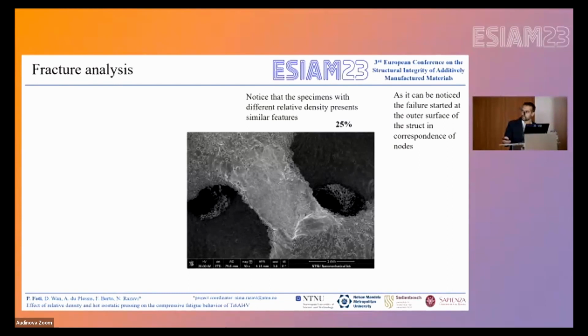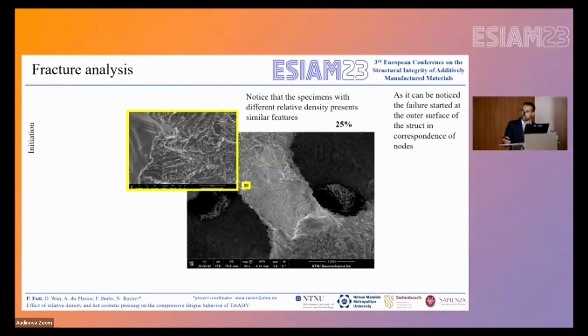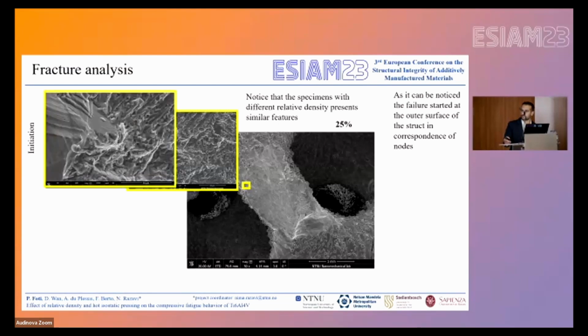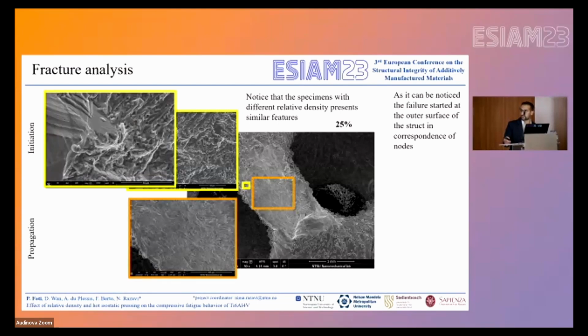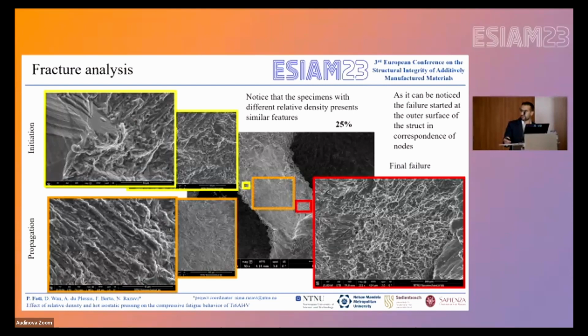Here you can see just one of the fracture surfaces, for the 25% relative density, but as I was saying before, there is no significant difference between the different relative densities and the different sets of specimens considered with the different post treatments. We can see the initiation of the fatigue failure, which started from the surface. Then we have the propagation phase, and finally the final failure.